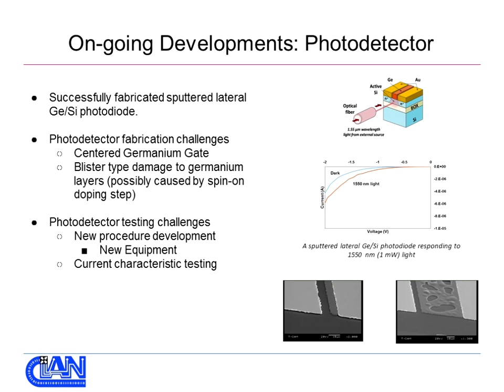But that was redone at the beginning of this year. The photodetector fabrication challenges that we're still facing, however, are the center germanium gate and a blister type of damage to the germanium layers. And we think this could be caused by the spin-on doping step that we use here. So we're constantly improving on our fabrication technique. But that's one of the major challenges that we're still facing.